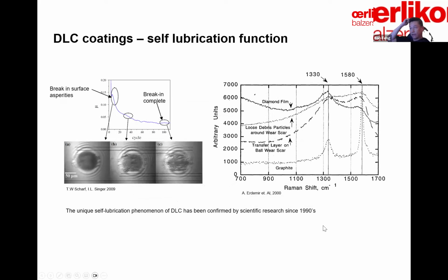So why is that? Why is there low friction for DLC? People at the Naval Research Lab, NRL, performed this creative experiment in the early 90s. What they did was use a DLC-coated steel ball sliding against a glass slide. Because the glass slide is transparent, they were able to use Raman spectroscopy to look at the contact interface from the other side of the glass slide.